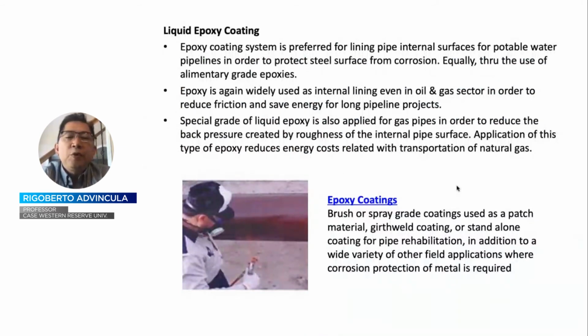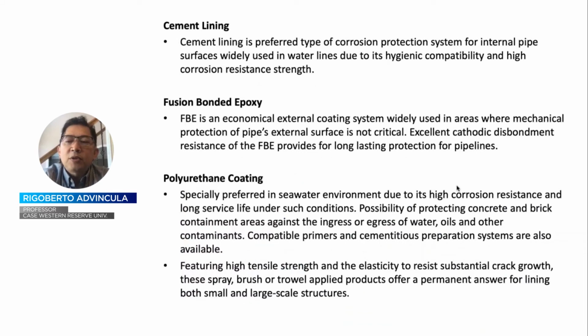You might have heard of fusion bonded epoxy or liquid epoxy coating, or some type of coatings that can be prepared as a dispersion and then heated or cured in the factory. Epoxy coatings, of course, can be applied in the field, but the use of epoxy as part of the factory installed coating is quite predominant. I'll show you some FBE projects in a few slides. But suffice it to say, other than FBEs, cement lining, asphalt lining, and polyurethane coating are different types of coating applications that can be factory installed.